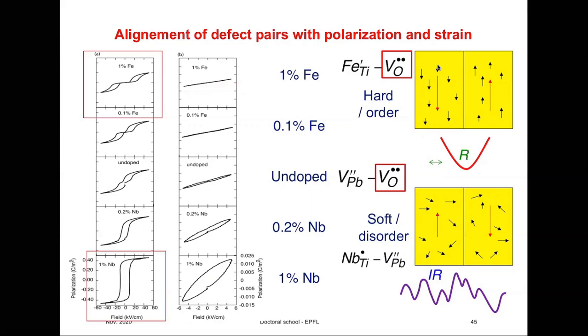If I apply bigger fields, then I will start opening the hysteresis as I explained before. But every time I come to zero field, the domain structure will come back because of these dipoles to exactly the same position. So this is the large field response. If you look at a soft material, both at weak fields and at large fields, you have a big hysteresis. So the field here is small, it's the same here and here. There is no hysteresis here at all, and there is a very large hysteresis over here, which is very interesting. And then for other compositions, as we go from 1% iron to 0.1 to undoped, 0.2 niobium, 1, we have almost continuous change in the properties, and something similar also happens at large fields.